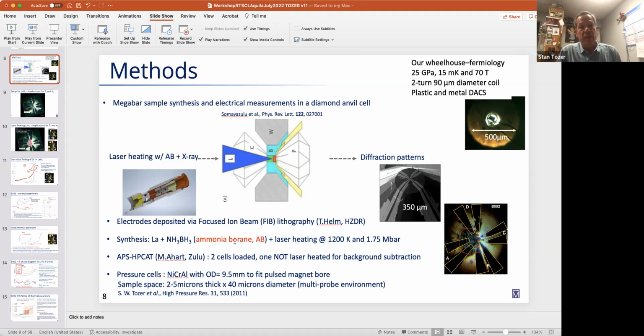So we have the small cell. We do what other folks have done. In this case, the gold leads or the tungsten leads that folks use are replaced by the FIBed electrodes that are shown here on top of the anvil and running down the pavilion, and then the sample is tacked to those electrodes, and AB is introduced. Pressure is brought up, and then we laser heat from one side.